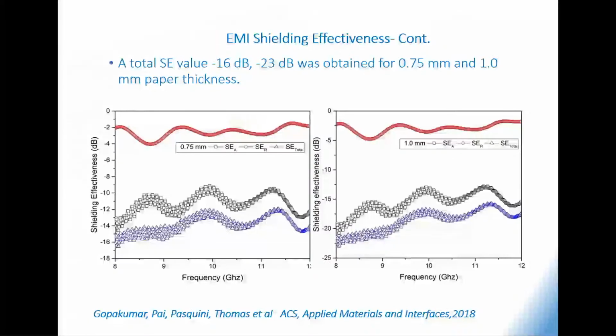We have a couple of patents on this. So we made several EMI shieldings using nanocellulose. Several types of protocols we have introduced. So this is one of the protocols we have introduced. Make nanocellulose, polymerize aniline on the surface of nanocellulose, and it's a wonderful shielding material. We could achieve up to 25 dB shielding. And this could be useful for your mobile phones and many electronic instruments.